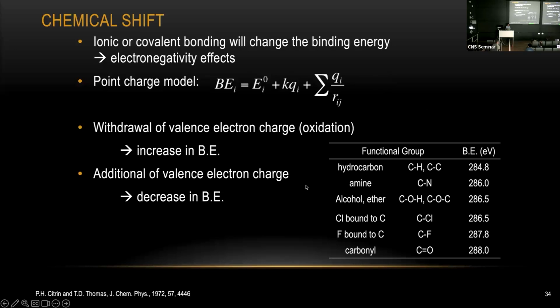And we are using the shifting of each peak to determine some chemical information. That's pretty much using this point charge model right here. Your initial energy depends on the charge around the atom, and also the environment around the electron you're detecting. That's how the energy can be shifted according to the chemical information. Simply, if you withdraw some valence electron, such as in oxidation, you're going to increase your binding energy. But if you add some additional valence electron to your atom, you're going to decrease your binding energy.